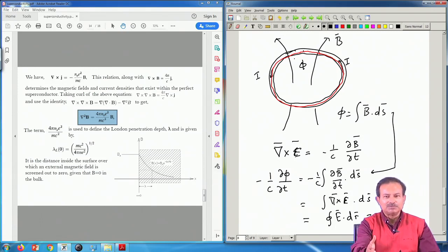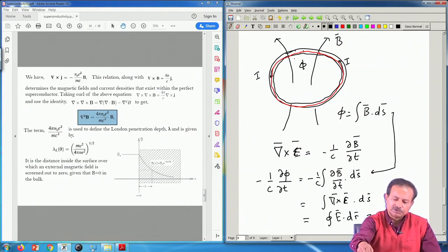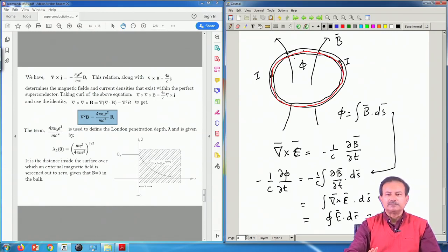What the superconductor will do is have a supercurrent which keeps on flowing through this, so that the field remains constant, at the same value. That is called a persistent current, a supercurrent. Since the flux has to be constant, the current also has to remain constant. So, it is a dissipationless current that flows in the superconductor, and it just keeps on flowing because no change in flux is allowed, and that is exactly what happens.